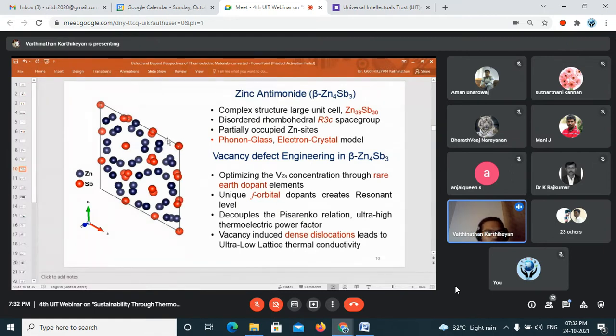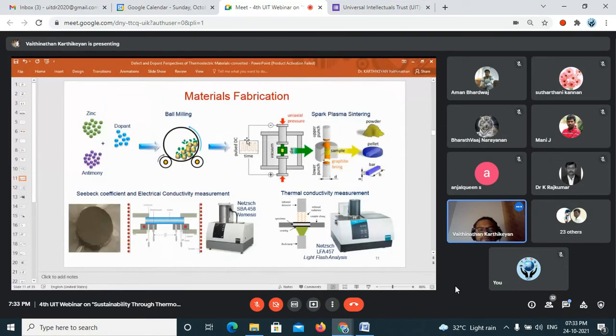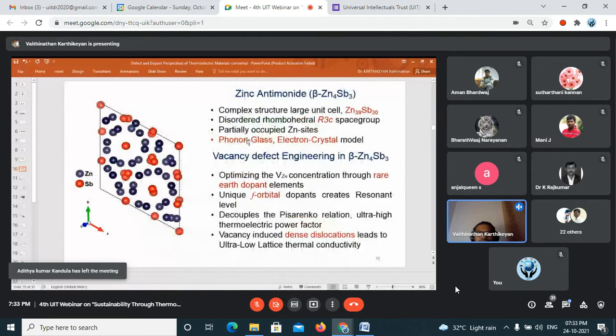Zinc antimonide is a compound having 39 zinc atoms and 30 antimony atoms in a unit cell, and the space group is R-3c. It is believed that theoretically zinc antimonide has a phonon glass, electron crystal structure. This is a well-known concept. What it says is this material conducts heat, I mean phonons, like a glass. You know that glass does not conduct heat like a metal. So zinc antimonide is believed to be like a glass for heat and like a crystal for electrons.